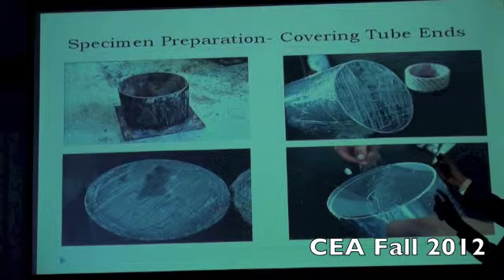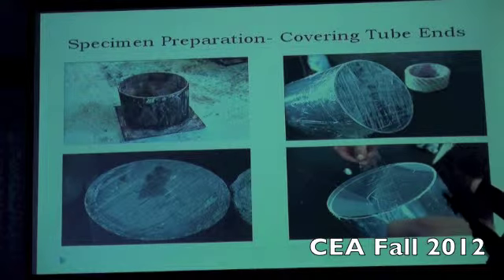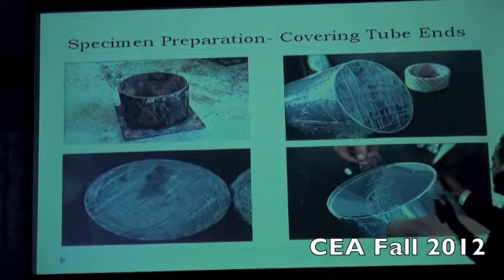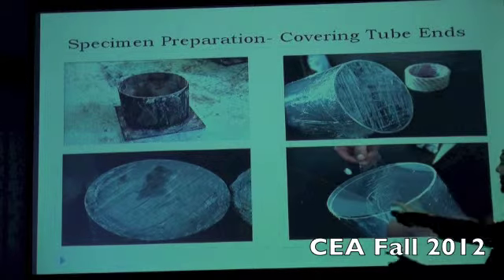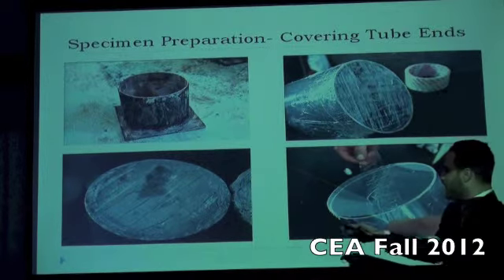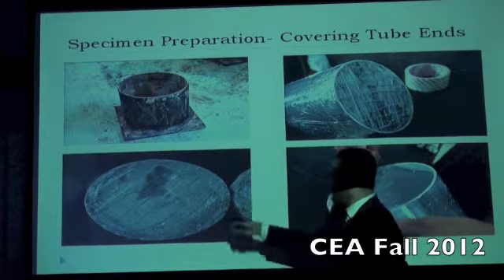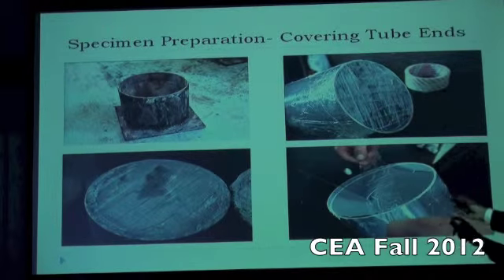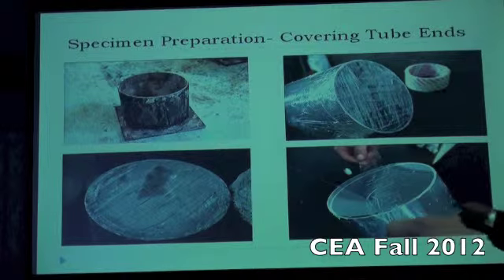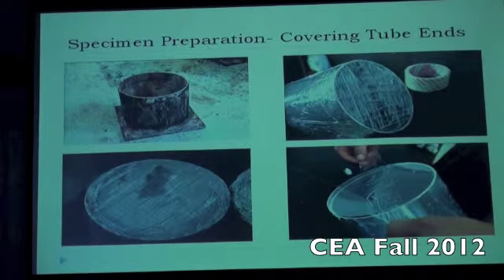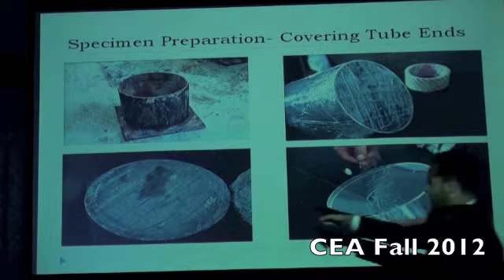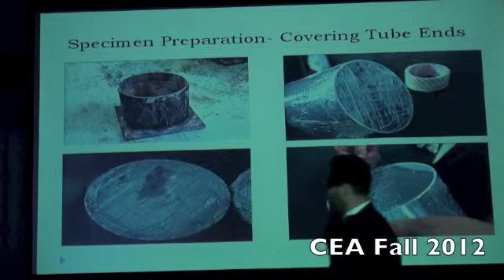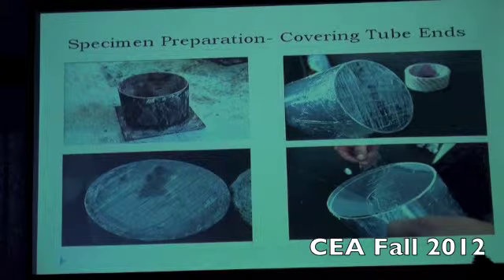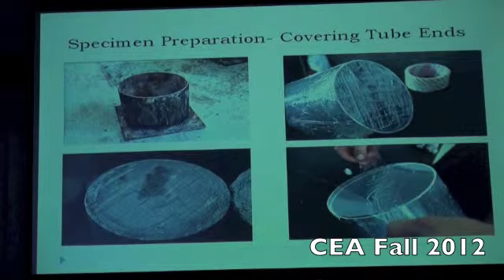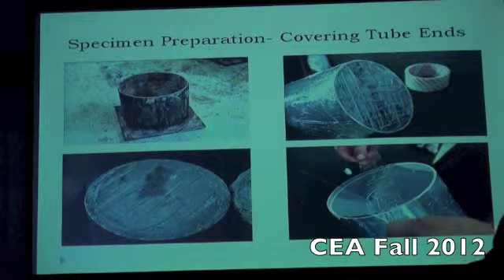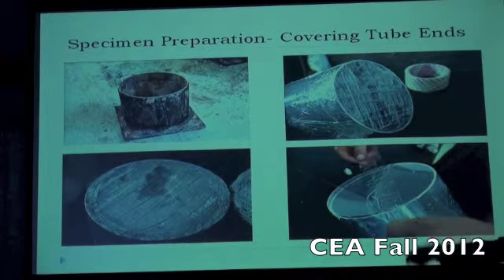So we thought of using a plaster like this to avoid it from moving. But we also did not get results as good as we were aiming for, as you can see here. So finally we used a circle of plastic sheet to avoid these marks in the concrete. But we also didn't get the perfect result we were aiming for. That's why we are going to do capping for all the specimens, and I'll show it later in the slides.